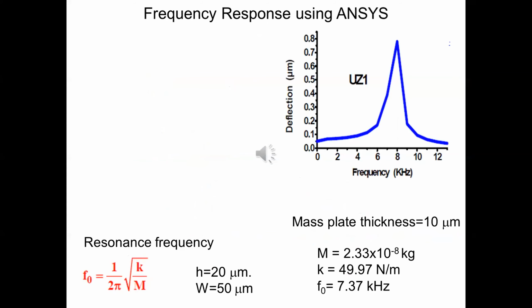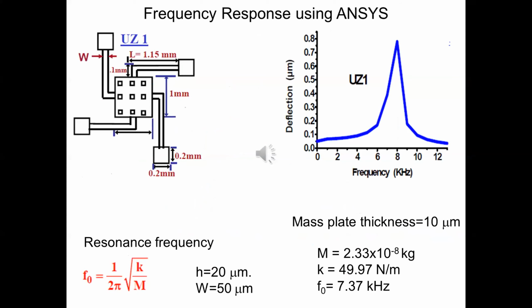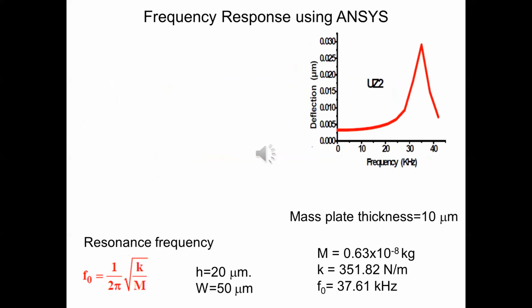Based on that, by using simulation, you can optimize the values of the length of the beam and the mass. So for this UZ1 structure, with a mass plate thickness of 10 micrometer, it has a mass of 2.33 x 10^-8 kilogram, a spring constant value of 49.97 Newton per meter, and a resonant frequency of 7.37 kilohertz. So this particular structure resulted in this.